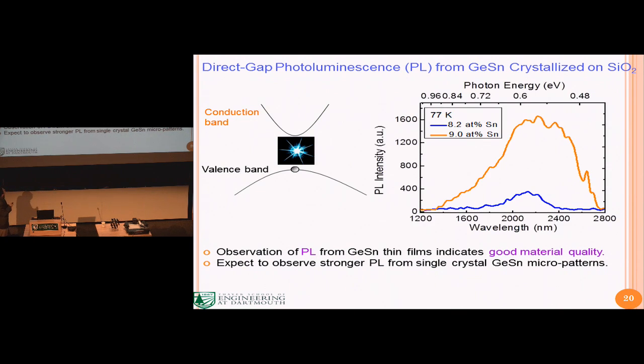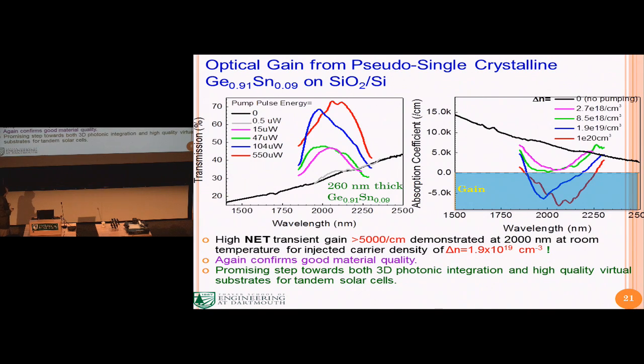So we performed this photoluminescence measurement at low temperatures. We do see the PL from the direct bandgap transition of the germanium tin. We expect that the patterned germanium tin will have even higher quality, but we're limited by the equipment. We don't have a micro PL system, but we will have that equipment arrive in March. So we'll perform some analysis on that part, hopefully getting even more impressive results.